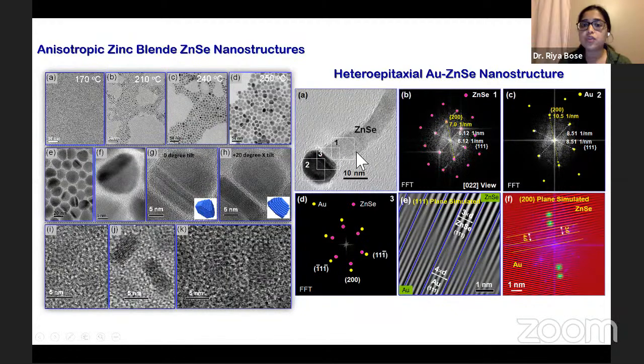And also, you can see the lines in the structure, and as I said, they are basically the lattice planes. So if you calculate the distance between these lines from the FFT, as shown in the images, from this distance you can determine which material it is and which crystal phase it is. So it's very informative. And not only that, when two materials are connecting, how their lattice planes connect with each other, you can also determine that from the junction. So here we can determine that 4 lattice planes of gold in a particular direction are connecting with 3 similar lattice planes of zinc selenide in one particular direction. And that's how we get very precise information about any structural transformation during the heterostructure formation.